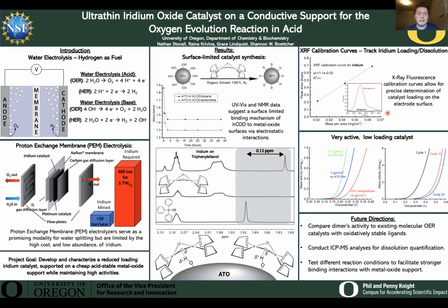This leads us to where we tested their electrochemical performance, where we ran what's called a cyclic voltammetry experiment, where you sweep between a known potential range back and forth and measure the current response. In this case, we're denoting it mass activity, which is simply current per unit mass. And what we're looking for is an earlier current response, as you see on the screen in the blue trace, both of which are our novel catalysts that we've developed, and we're comparing it to iridium oxide nanoparticles, which, as you can see, are significantly less active. This is likely due to the fact that bulk iridium nanoparticles cover each other's active sites, making the overall catalyst less active, as opposed to our catalyst, which is very thin, where most of the iridium active sites should be present to the solution, allowing for those iridium active sites to facilitate the oxygen evolution reaction.